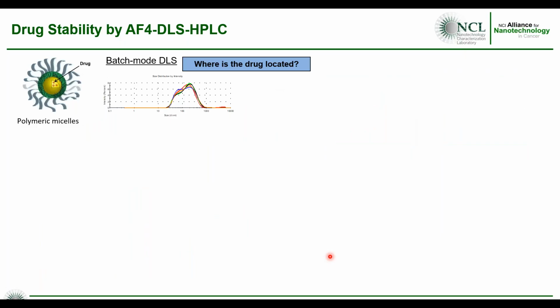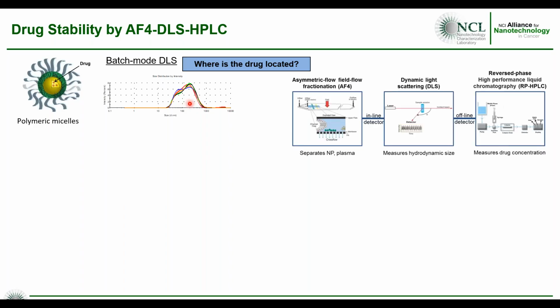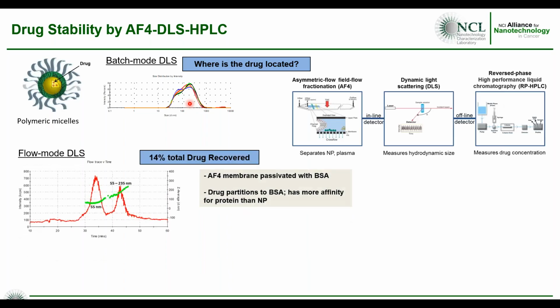Here's another example, and this time we're using a polymeric micelle. If we look at the batch mode DLS, it's actually more of a mess than the previous example. Again, where is the drug located? We're using AF4 DLS with offline reverse phase HPLC. In this case, you can see AF4 can separate out the 2 populations with 2 different size ranges, a constant 55 nanometers and an increasing size population. In this case, we're only seeing 14% of the total drug recovered. Again, this implies that a lot of this drug is partitioning to the protein.